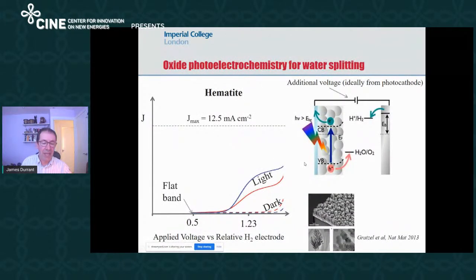Another way of saying that is if you plot the performance metric for a photoanode, and this is typical data for hematite from Michael Gratzel, and this is pretty much state of the art, this is the current voltage curve for oxidizing water on a hematite photoanode. In the dark, you have to apply a large potential, large compared to 1.23, which of course is the equilibrium potential for splitting water.